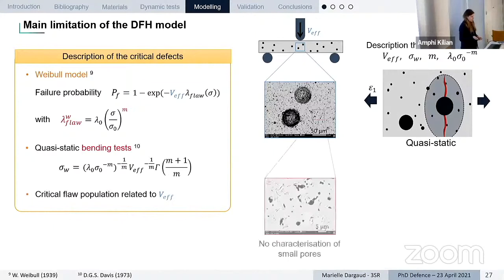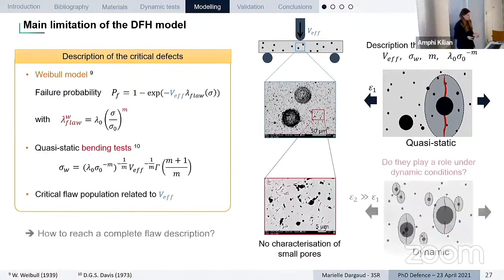volume. However, if we zoom in, for example, this material, we can see that we have all the defects, which are here porosity, but are way smaller. And these defects are not going to be triggered during a quasi-static bending test. So the big question is, do we actually need to characterize these defects and implement them in the model to have a good characterization of the behavior of the material?